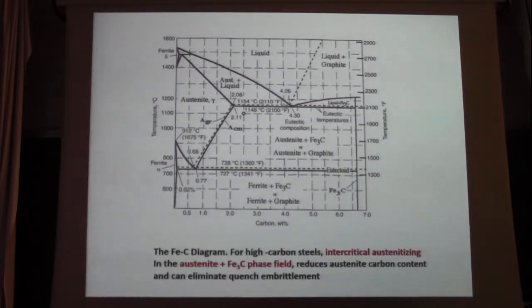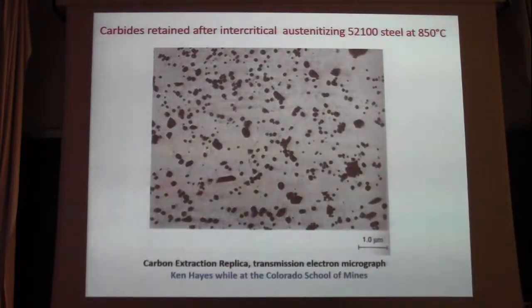This is typically applied with bearing steels. Bearing steels are a tremendous application for quench and temper high carbon steels. And those are typically austenitized around 850. And this ACM boundary gets shifted because of the chrome content of that steel. So you definitely austenitize where you're forming cementite. And here's an example of that type of microstructure.